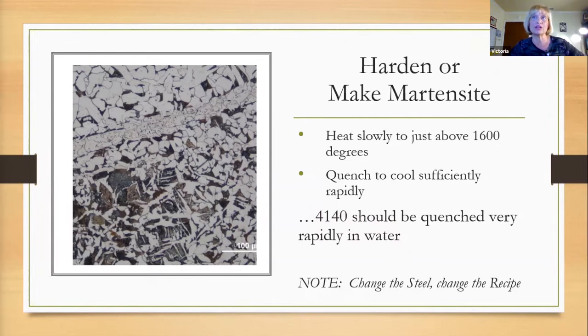And again, at the atomic level, what has happened is that carbon was captured inside those iron structures, making wedges that interlock all together. And this is a photo I showed in that basket handle talk with a lot of welding. This is a magnified view of a cross section of the weld. Here's the weld. And you can see these sharp needly things. That was martensite. That's an interlocked structure. So if that helps you visualize what's going on, that's what it looks like under a microscope.